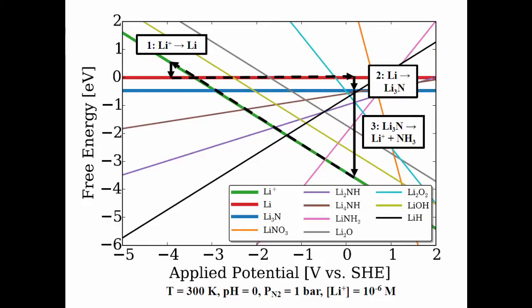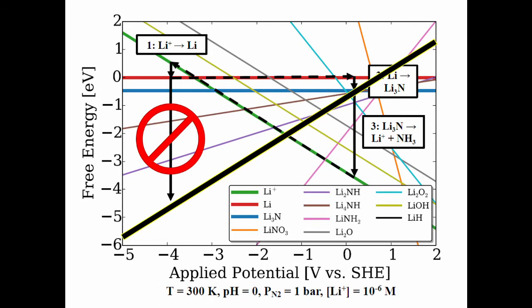An important advantage of this cyclic process compared to the direct electrochemical route is that it physically and temporally separates the activation of nitrogen from subsequent protonation steps. This avoids unwanted thermodynamic sinks such as lithium hydride and allows for much better selectivity towards ammonia.